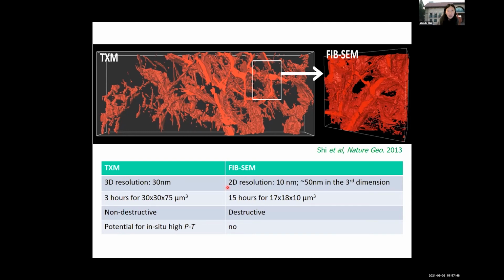And so the resolution for both techniques is pretty similar. SEM has a benefit in the 2 dimensions, but you lose some in the fibbing direction. Also, a benefit of nano-TXM is that you can look at a larger sample faster, and that is a potential for in situ, complex environments and imaging things in situ.